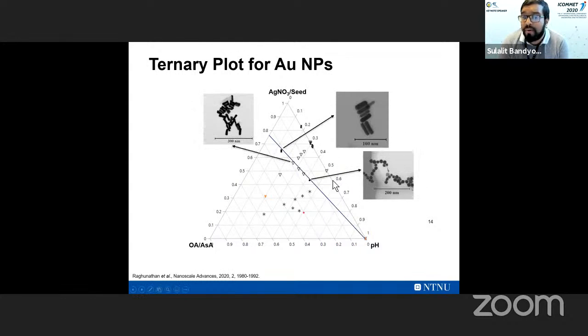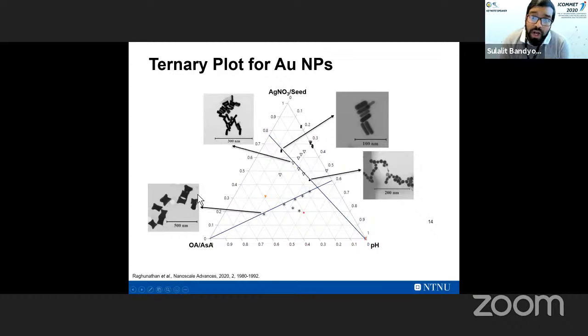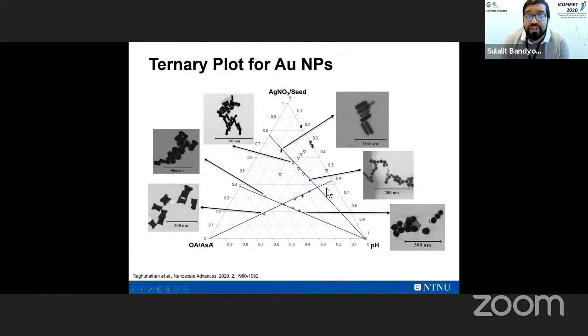So we are able to go from spheres to H nanorods to perfect nanorods. In another tie line, we see that there is no specific shape change, which is the nanomakura shape. A makura is a Japanese word for pillow, so these particles look like a three-dimensional pillow. Along this line, there is no change in the morphology. And along another line, we see changes from tetrahexahedra to more multifaceted structures.